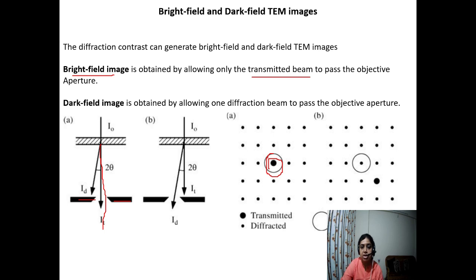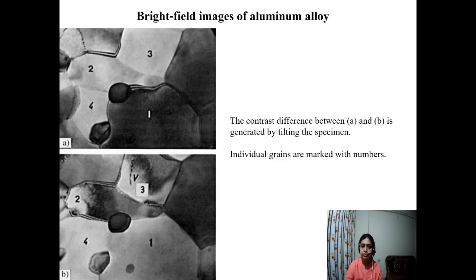So the dark field image is obtained by not allowing the transmitted beam through the objective aperture. However, for a bright field image, we allow the transmitted beam to pass through the objective aperture. So this is the main imaging mode in the TEM machine, bright field and dark field. In bright field, the transmitted beam is allowed to pass through the objective aperture, and in the dark field image, only the diffracted beam is allowed to pass. In this way, we can get a lot of information with a combination of both bright field as well as dark field. So this is an example of bright field images of aluminum alloy.